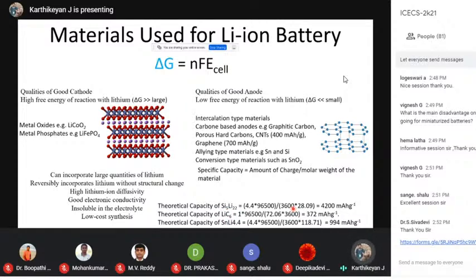The problem with silicon is its pulverization and poor interparticle connectivity. It's a kind of alloying material. Dr. Reddy was already discussing that. When you add lithium to the silicon, it makes an alloy with the lithium, and during this alloy formation, there is a huge volume expansion, roughly 400%. That means it increases its volume 4 times. That's not a desirable thing, because when you charge your battery, if the anode side is suddenly bulging, it is not going to be safe, right? Your battery may blast. But if you go to carbon, it is very safe, but the problem is it has very low capacity.